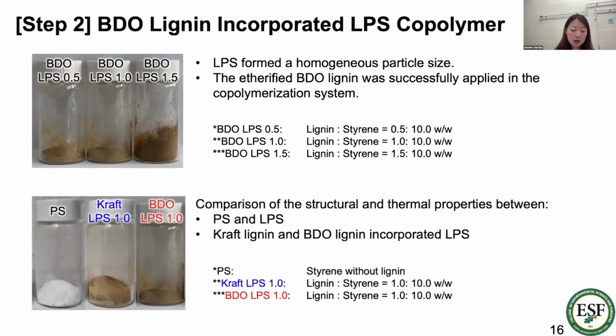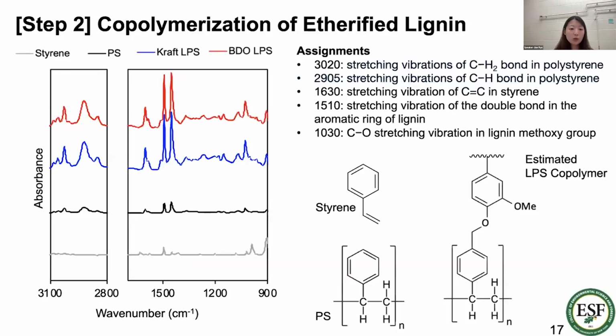To compare each of the polymers we produced, we prepared polystyrene, which doesn't have any lignin material in the polymer system, just styrene to polystyrene. And we used both Kraft lignin and BDO lignin at around 10% concentration of modified lignin. So, starting with the structure, to identify the structure of the polymer,